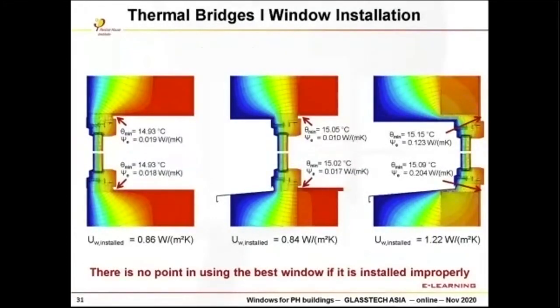Well, last but not least, the installation of the window is quite important. Here a simple example. If you go for the window to install on the masonry wall, you will have a very high psi value, so very high heat losses here. Only if you go for the installation of the window in the thermal envelope, so within the almost straight line with the thermal insulation layer, then the psi values can be as low as possible.